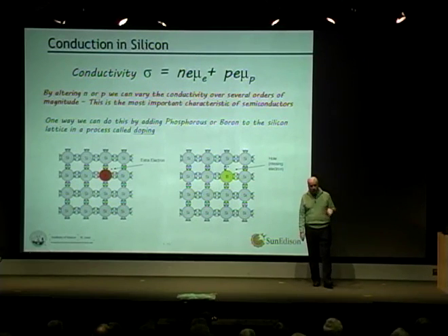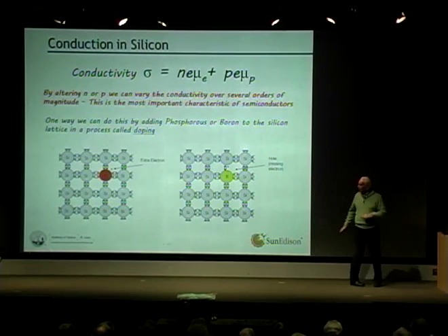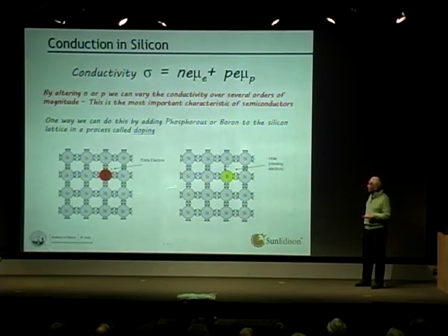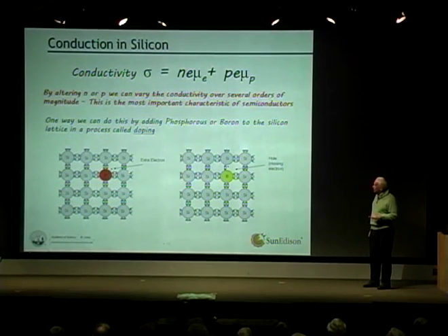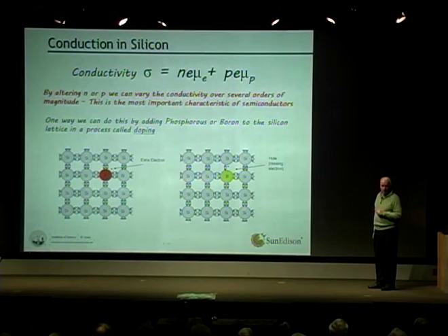So the question down the front here, in case you didn't hear it, is in both of these cases, are we increasing the conduction? And the secondary question is, well, isn't one better than the other? And the answer is actually yes, and that is because we have two mobilities here. In this case, this is the number of electrons times the mobility of the electron, and the number of holes times the mobility of the holes. And I can tell you that in silicon, at least, the mobility of the electron is much faster. It's about three times faster than the mobility of the hole.